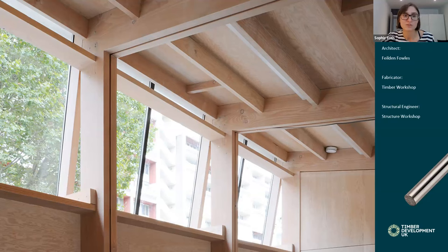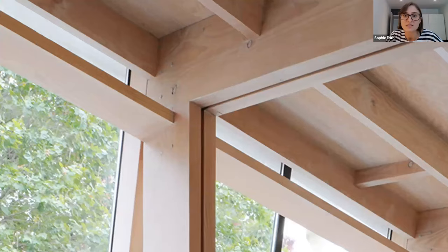And like with bolts, you typically see dowels with diameters ranging from 8 millimeters to 30 millimeters, but with dowels, your hole cannot be larger than the dowel itself because it needs to have a tight fit. So this puts more onus on workmanship, which could result in increased costs. But if you don't like the appearance of bolt heads and nuts, then they can be a really good choice. In this example here, dowels are used to connect the rafters to the columns, and they're so discreet you can't even really see them. You can see the four tiny dowels positioned in the corner there.